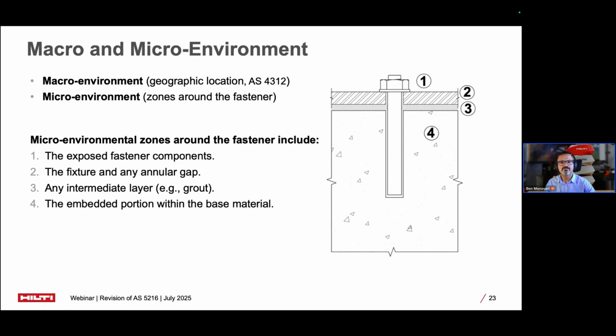The framework identifies 4 distinct zones: the exposed fastener component, the fixture and any annular gap, intermediate layers such as grout or sealant, and the embedded portion within the base material. Each zone can have different corrosion risk and exposure conditions. For example, the exposed portion might face severe marine conditions, while the embedded portion is protected within concrete. This detailed assessment enables more accurate durability predictions.